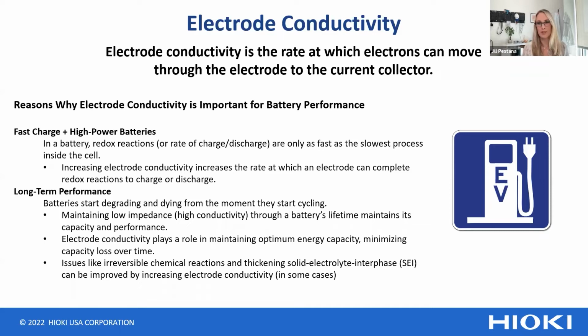And it won't damage the cell as much, because we could go really fast for charge, but we may damage the materials, which leads to the second point. The long-term performance of a cell is definitely affected by the electrode conductivity. Batteries start degrading and dying from the moment they start cycling, unfortunately. And it's all about gently letting them die, right? We're going to be cycling them.